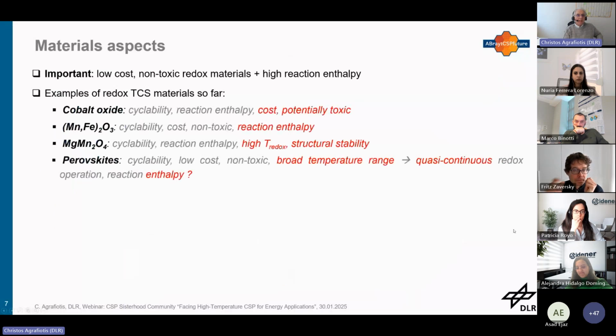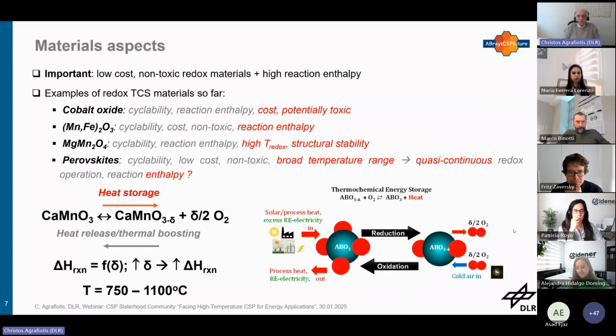So that's the concept. Now the material aspects. This is interesting, but what are the materials that we can use to do it? There are several materials that have been tested, like cobalt oxide, manganese, and so on. The first of them have different disadvantages like cost, toxicity, low reaction enthalpy, and so on. So now we concluded that we're going to deal with perovskite materials, that are made of low-cost, non-toxic, earth-abundant elements, and they operate in a quasi-continuous way.